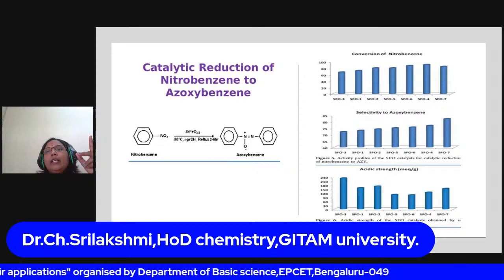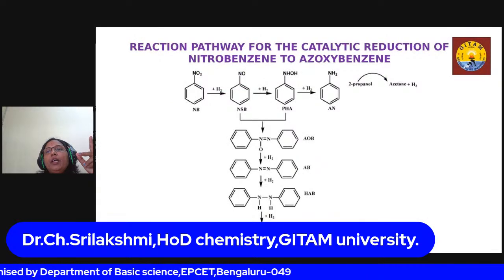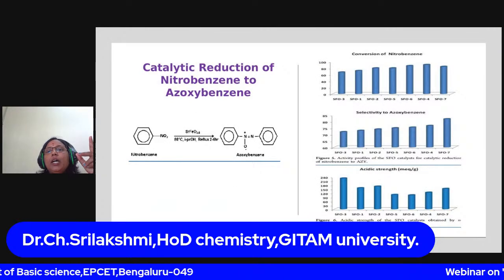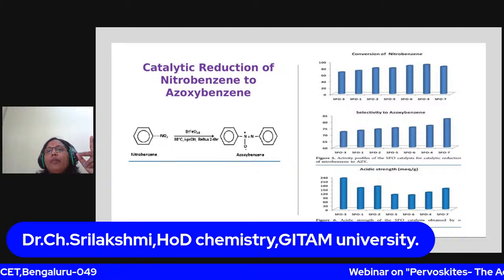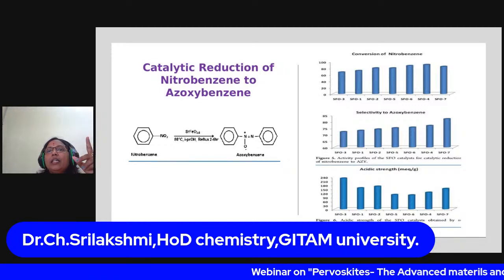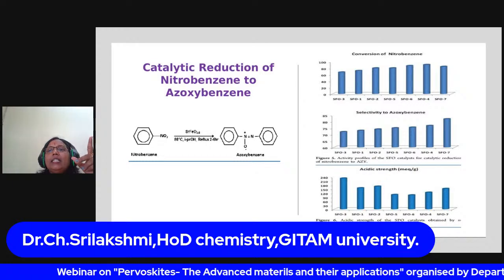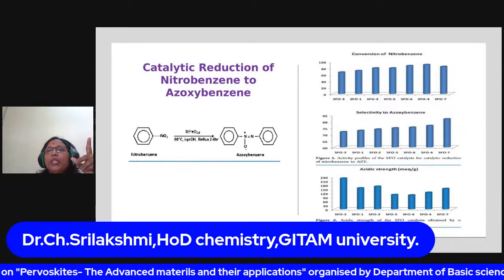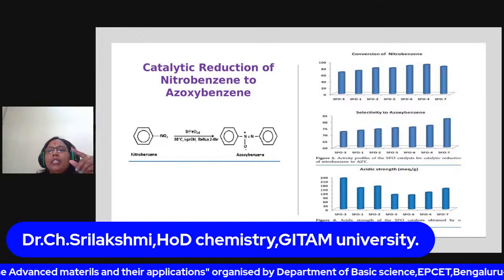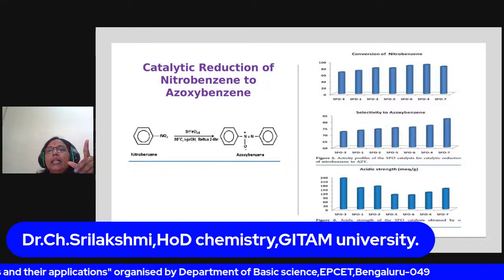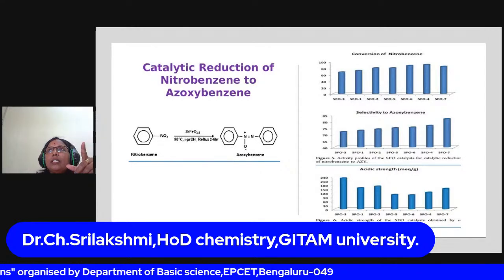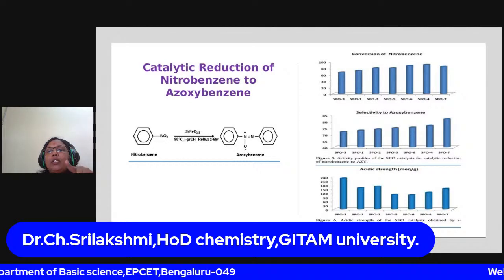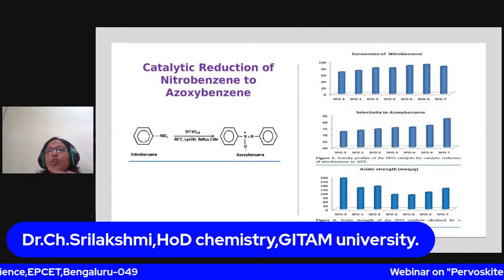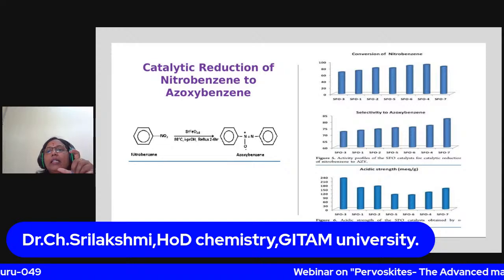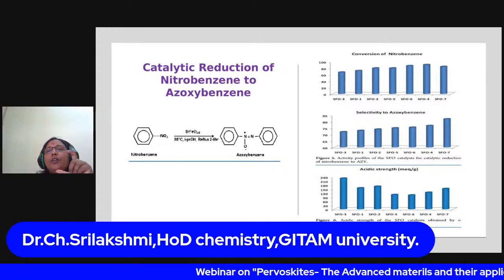You can see these three are the samples prepared using individual fuels, and from 5 to 7 the mixture of fuels. So the conversion goes up, and the selectivity also goes up. There is no correlation between conversion and acidity, because here acidity is more in the samples synthesized using individual fuels, but not in the samples synthesized using a combination of fuels. So here the acidity is related to the selectivity.